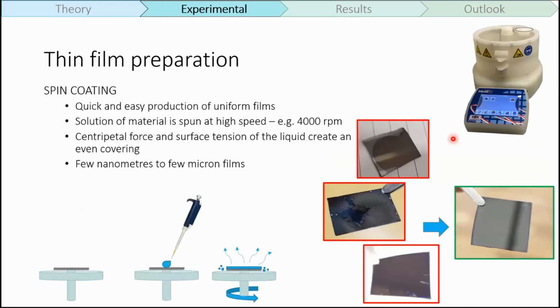As I already mentioned, we use spin coating for the production of uniform thin films. A spin coater can be used to produce very thin films. In this method, a certain amount of liquid or solution is deposited in the center of the substrate and can be spun from 10 rotations per minute up to 8,000 rotations per minute.